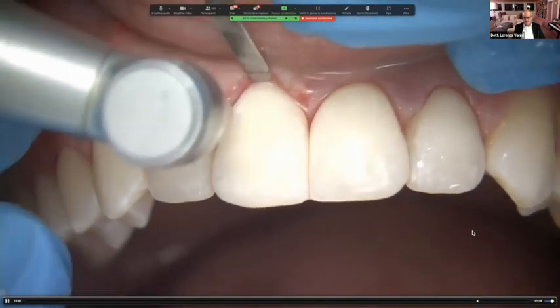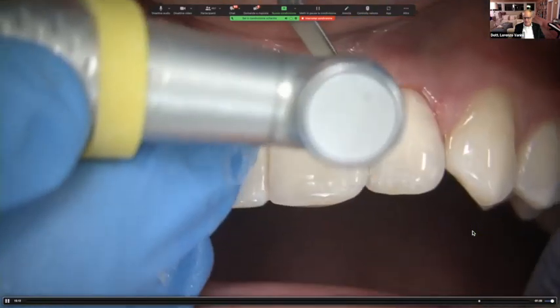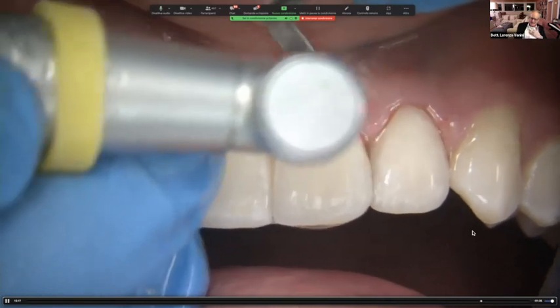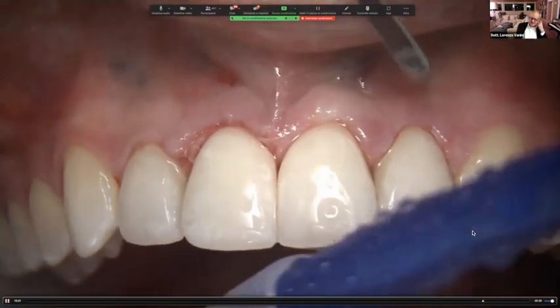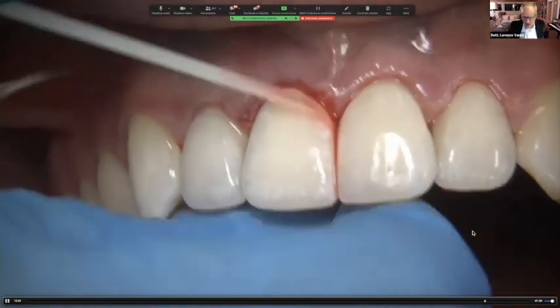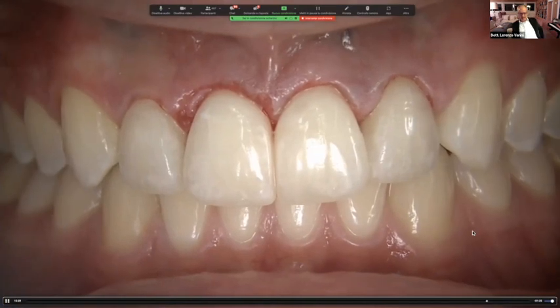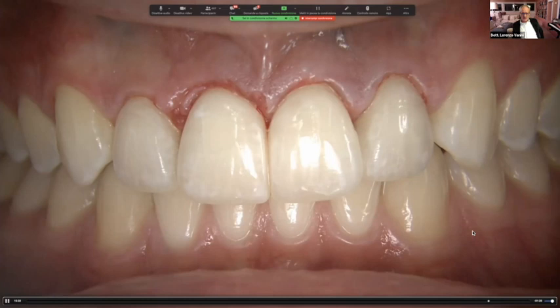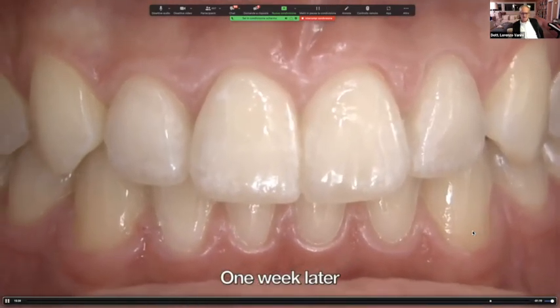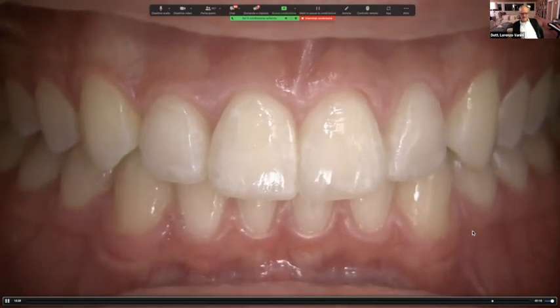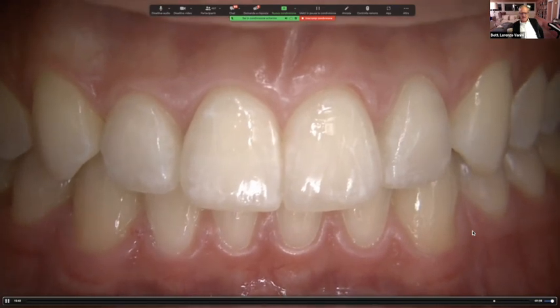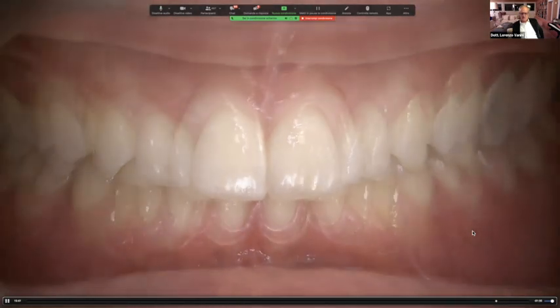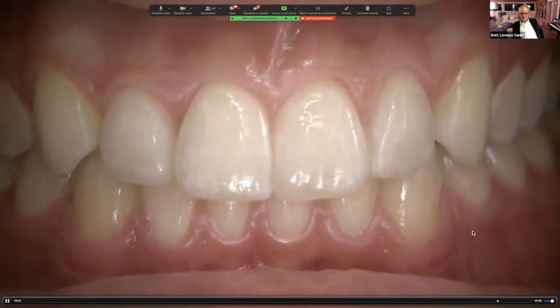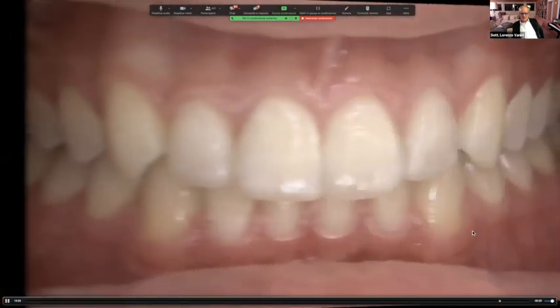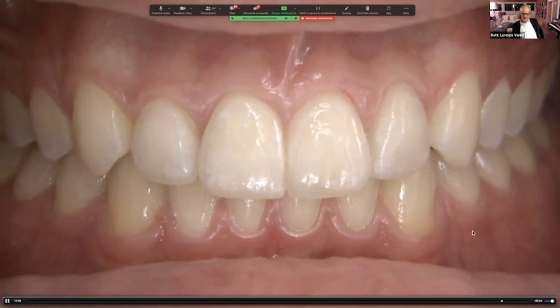It's a rubber point. It's not abrasive on the ceramic, but it's abrasive for the bonding of the cement. So it allows you to have a very clean surface around the margins. In the interproximal area, I use tapes, and this is 1 millimeter. You see, it's very, very good, the final result. We achieve a very good color match.